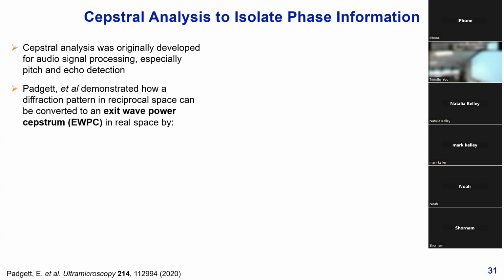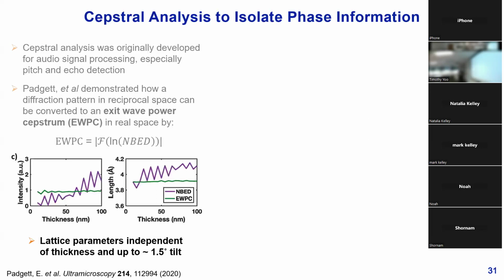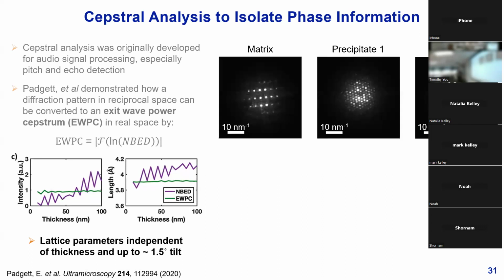We'll just call these cepstrum patterns for now, by a simple equation of just the Fourier transform of the log of the diffraction. And so what they showed here was that by applying cepstral analysis, the intensity of the spots within the cepstral patterns was uniform across a range of thicknesses, as well as some amount of bending. And so that already makes it a really good motivator for trying to run our own data in this case, because that's sort of the problem we're seeing here.